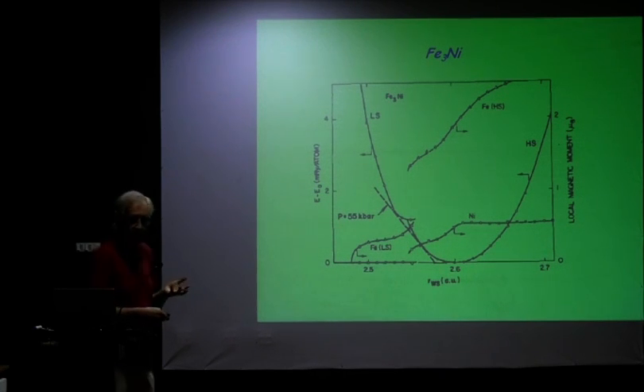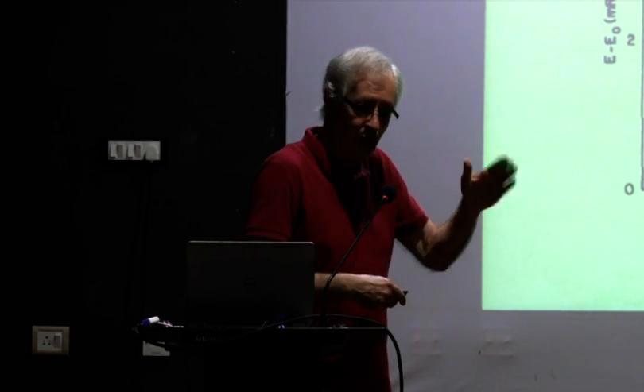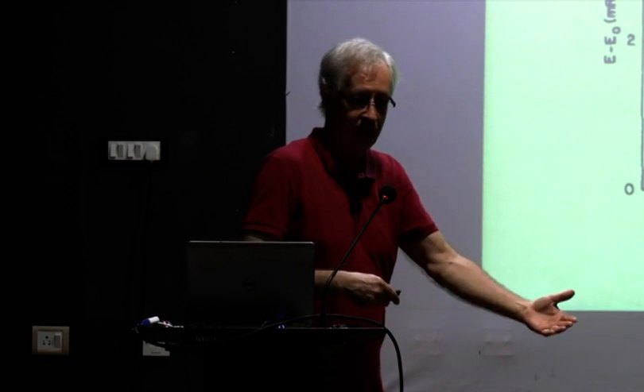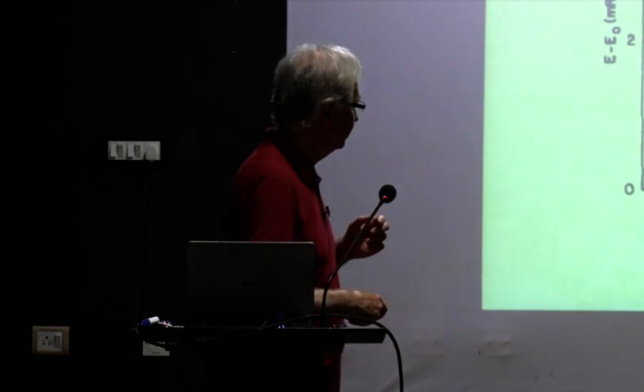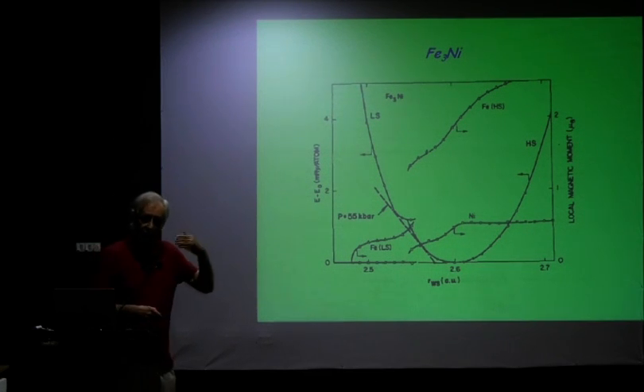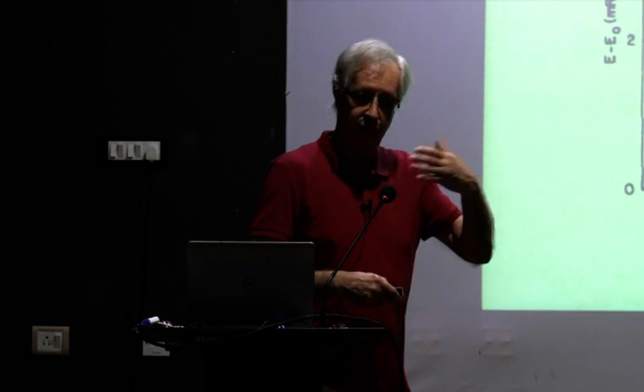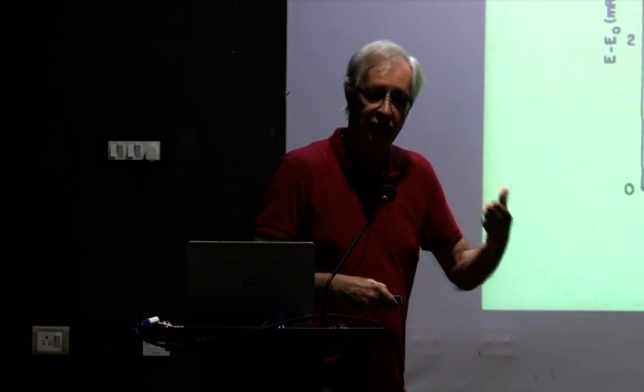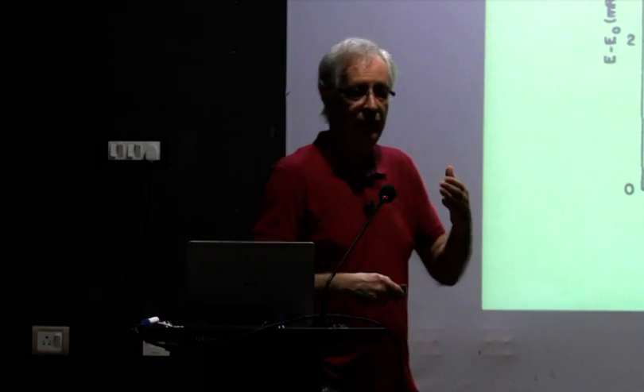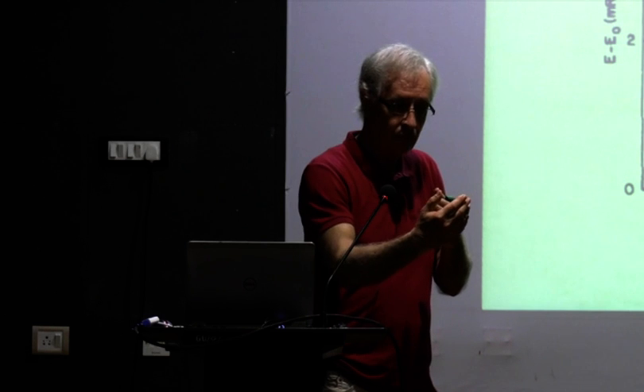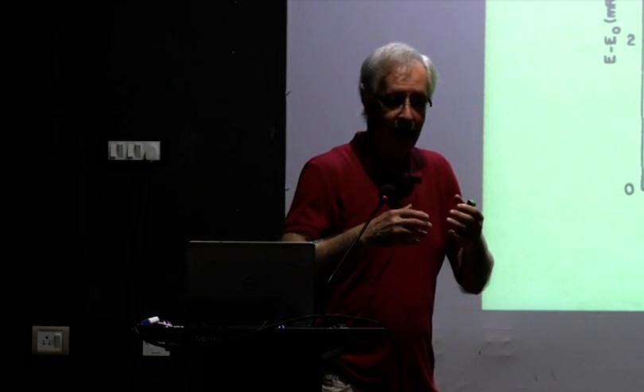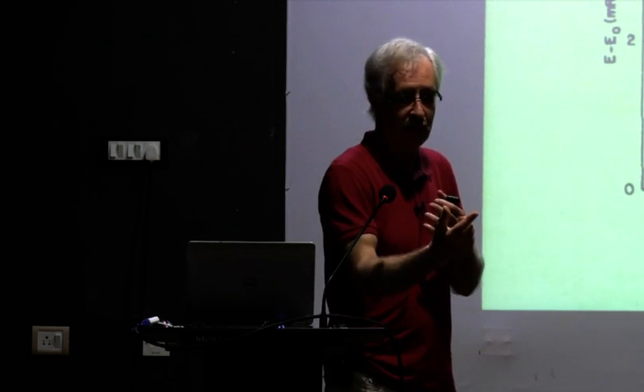This difference here, as I said, is about 10 millielectron volts. So if we start increasing the temperature, we're going to have an effect of coming more and more towards the low spin state. So we can go to smaller volumes. In the other one, it was going to larger volumes. So what is happening then? The system is expanding normally. Okay? It has a normal thermal expansion. But then as you increase the temperature, if you're going more and more into the low spin state with increasing temperature, which is at a smaller volume, then this effect is counteracting the normal expansion.